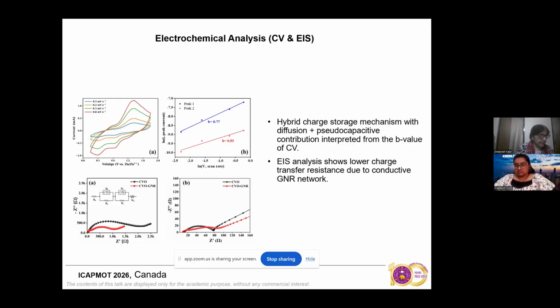So 0.53 corresponds to a diffusion-limited process, where the typical ion intercalation is there, and 0.77 denotes a dominant pseudo-capacitive response. So we have the hybrid charge storage mechanism with diffusion and pseudo-capacitive contributions.